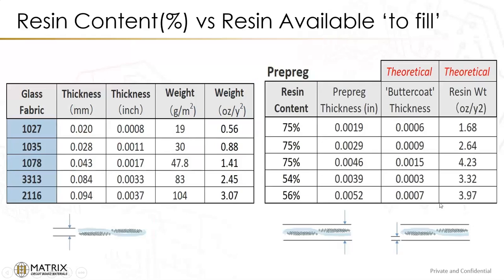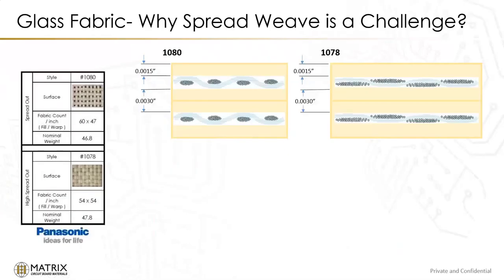But it's something that at least we should talk about when you're trying to discuss optimizing thickness versus the amount to fill. So what Bob was talking about is if you're putting multiple plies together, and let's say for theoretical purposes we've got 75%, about 1.5 mil on the surface of each of these plies, that means we have 1.5 mil on the inside where these two plies are together, which actually doubles the amount of resin in between the two plies. So that's all good because we have additional resin available there.